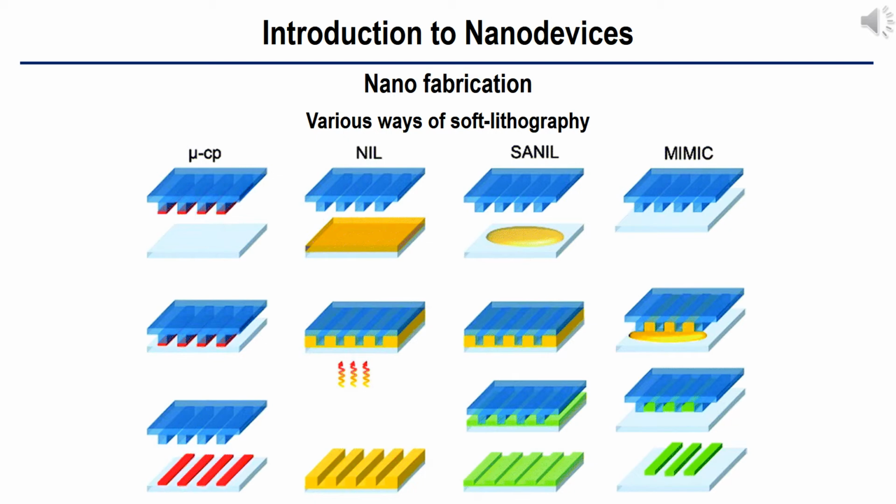The second one is nanoimprint lithography, as shown in the second case from the left. As was used in microcontact printing, nanoimprint lithography uses a mold as a stamp. However, the mold is hard, for pressing into the pre-deposited polymer or inorganic substrate. For the mobility of the pressed layer, the process can use higher temperature or solvent atmosphere. After releasing the mold, the underlying pressed layer is developed and treated for hardening.